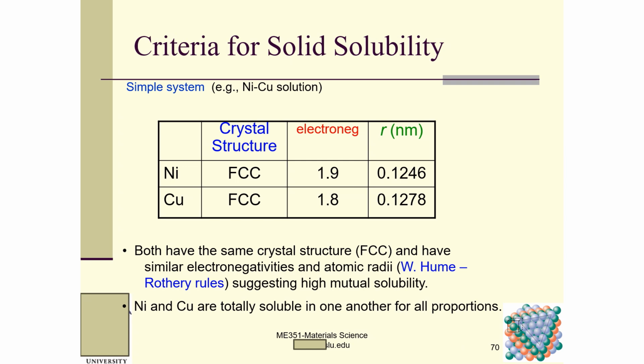So in order to have an isomorphous binary phase diagram, there are some criteria that need to be met for solid solubility. A simple system, for example, is nickel and copper. You can see the crystal structure is FCC, and the electronegativities are 1.9 and 1.8. These two must be very, very similar.